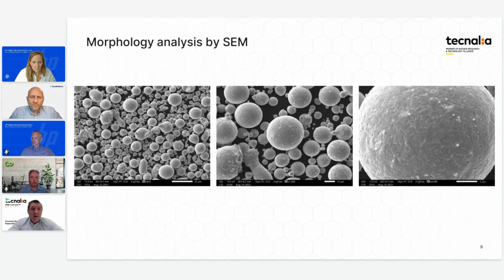We also evaluated the morphology of the powders using the scanning electron microscope. It is important to have, as I said before, spherical particles that certainly will help the flowing properties of the powder. We are looking for nice spheres with few satellites, no hollow particles. So here you can see images taken at different magnifications, in which you can see that the sphericity of the powder is rather high, still some elongated particles, if you want, but very few, and very few satellites as well.